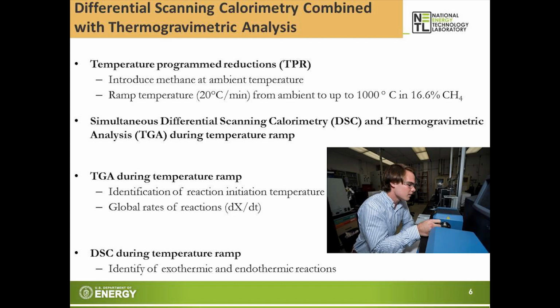The other technique we use for the initial evaluation is differential scanning calorimetry combined with thermogravimetric analysis. Now, for this test, we place the solid material in the reaction pan and introduce methane at ambient temperature. Then we do a temperature ramp from ambient to 1000 degrees C in methane. And we do simultaneous differential scanning calorimetry, DSC, and thermogravimetric analysis during the temperature ramp in methane. Using the TGA data, we can identify the reaction initiation temperature as well as global reaction rates. And then with the DSC, we can identify the exothermic and endothermic reactions during the ramp.